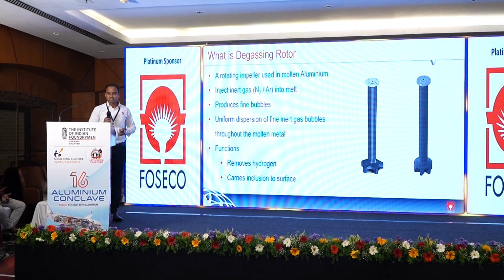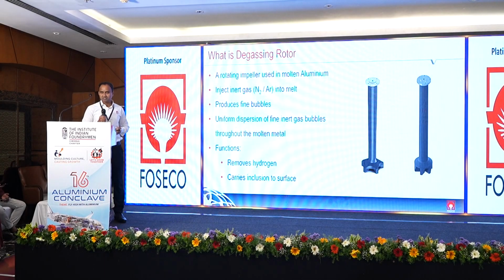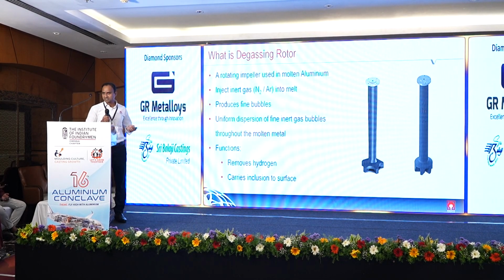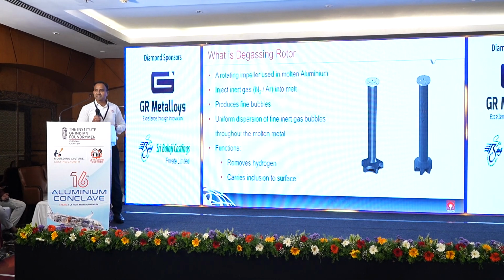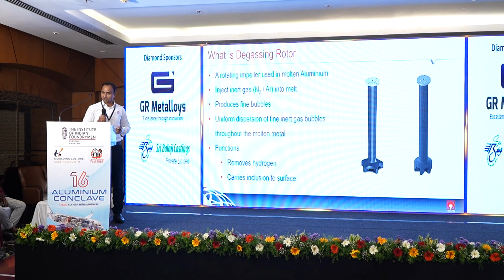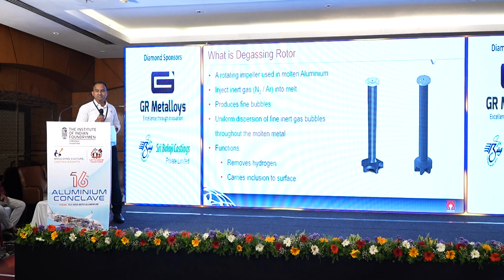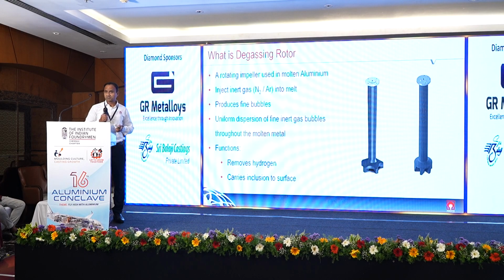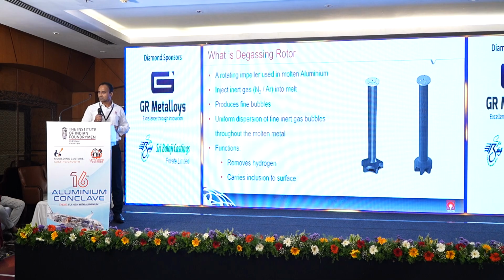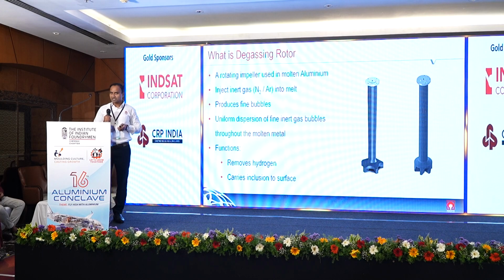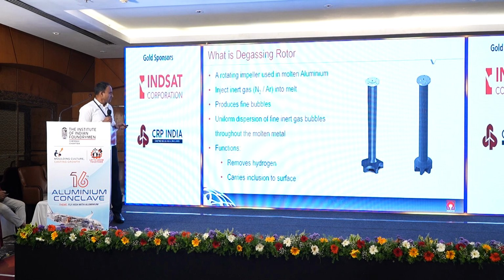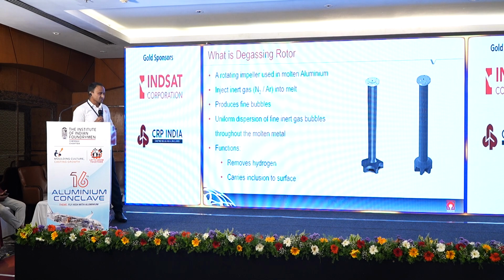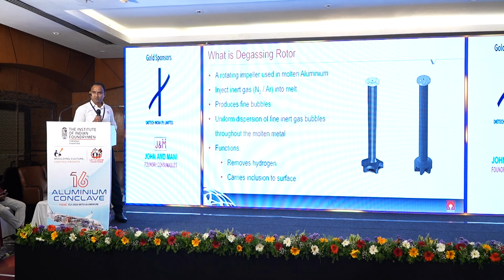So what is a degassing rotor? This is an impeller, a rotary impeller, made of many materials like graphites, ceramics, silicon carbides. It injects inert gases like nitrogen or argon through the shaft, and these rotors split the nitrogen inert gas bubbles into small fine bubbles and uniformly distribute them throughout the molten metal. So it will absorb dissolved hydrogen and carry it to the surface, and remove hydrogen from the molten aluminum. So the main function of this rotor is to remove dissolved hydrogen from liquid aluminum, as well as to remove fine inclusions from the liquid aluminum.